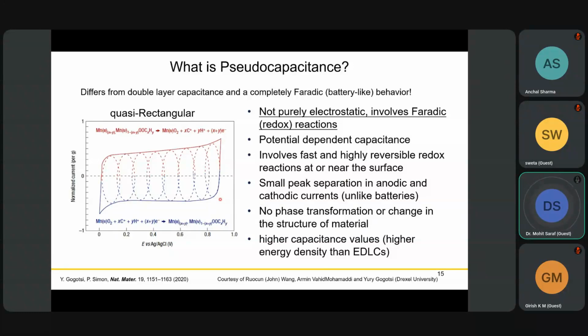When you perform cyclic voltammetry, most likely your anodic and cathodic peaks will be at the same potential, so the peak to peak potential will be very minimal. As I mentioned, there is no phase transformation and no change in the structure of the material, so it gives you slightly higher capacitance than the double layer capacitors.